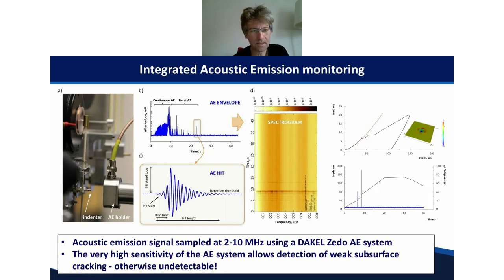So my other example is again taking advantage of the open geometry of the system, and this is another module that we offer, the integrated acoustic emission monitoring setup, which you can see here on the left. So this allows us to look at the acoustic emission envelope as a function of time in some degradation in any type of test, like an indentation, scratch, impact, whatever. But also we've got this very high frequency, high sensitivity monitoring, and this allows us to look in much more detail at the actual hit spectrum, spectrographs, and in this example here on the right we can see, for example, a couple of pop-ins in the spherical indentation.